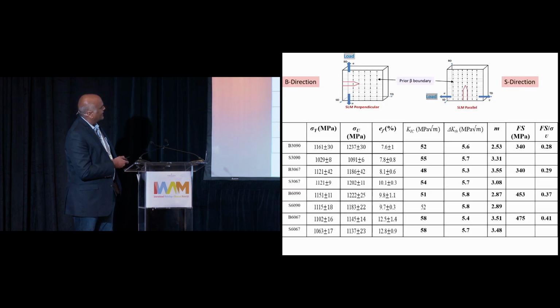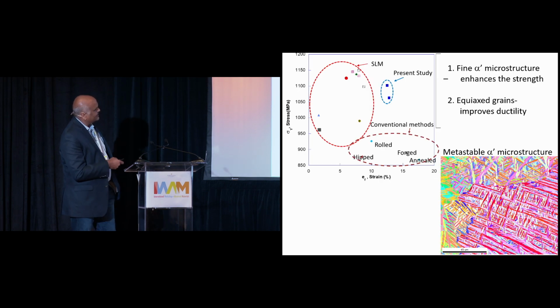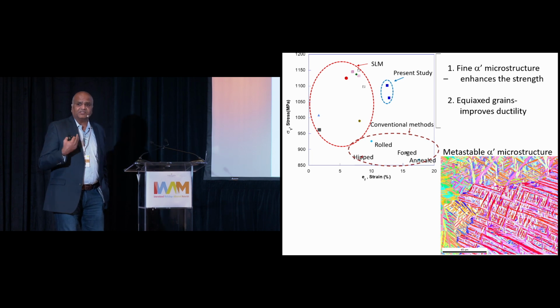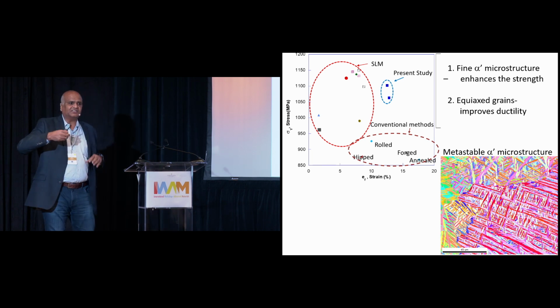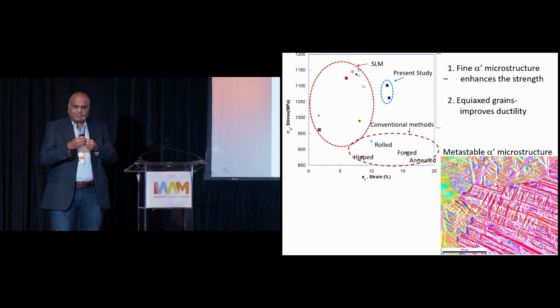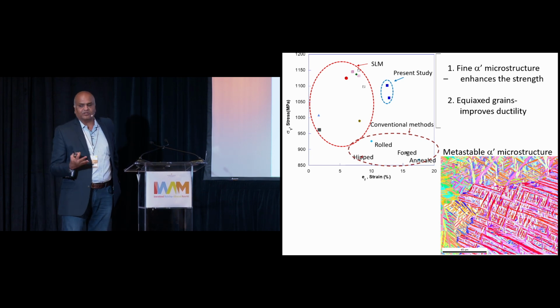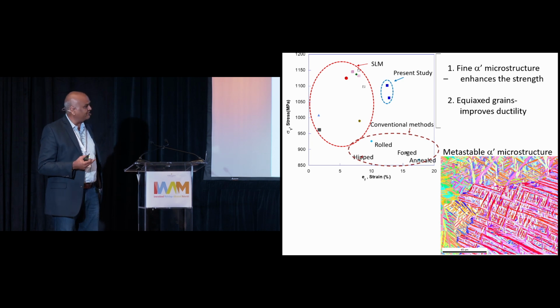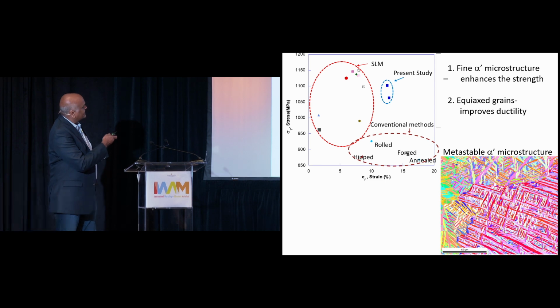We measure the mechanical properties. One of the things that happens is, at any given instant, you're melting a very small voxel of material sitting on a huge plate, so rapid solidification conditions prevail, and you get a martensitic metastable alpha prime microstructure, which gives this material very high strength.